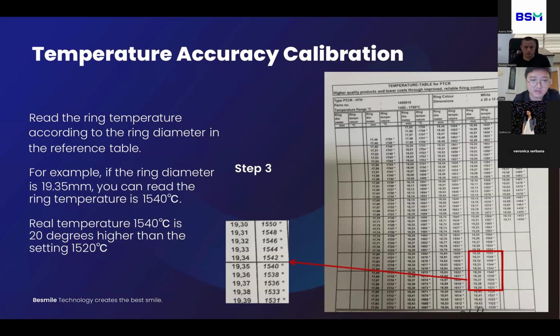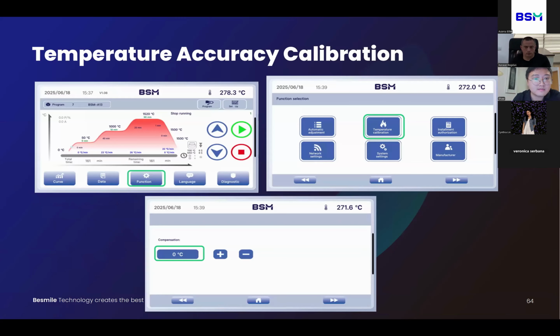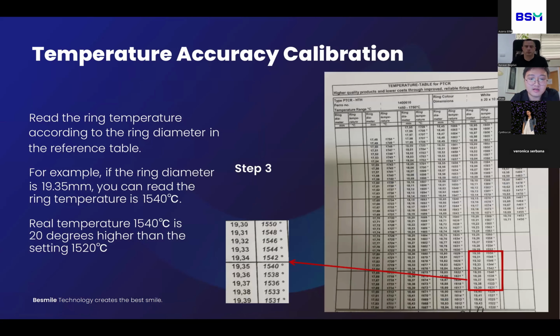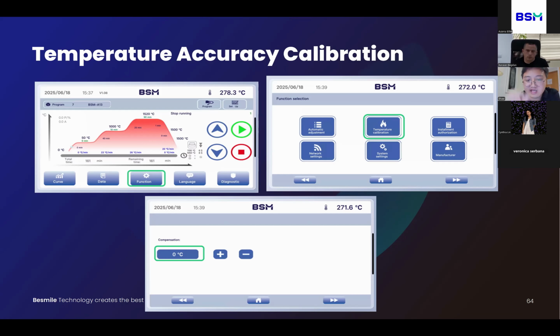So how can we calibrate the temperature to make them match? First, we enter the function menu and then choose temperature calibration. Here you can see there's a compensation value for the temperature. If the real temperature is higher, you just need to decrease this value. If the real temperature is lower, you just need to increase this value. For my example, the real temperature is 20 degrees higher, so here you can enter minus 20 based on 0, replacing the current 0 compensation. And then you can finish the temperature calibration.